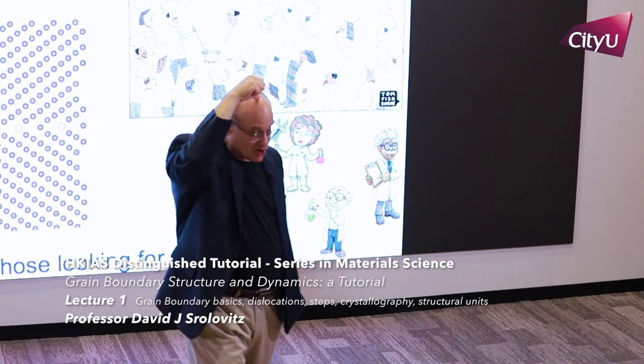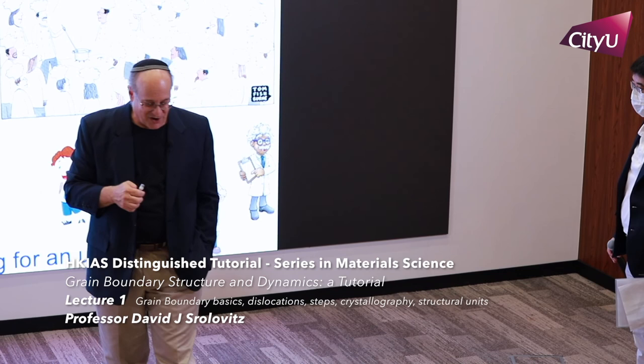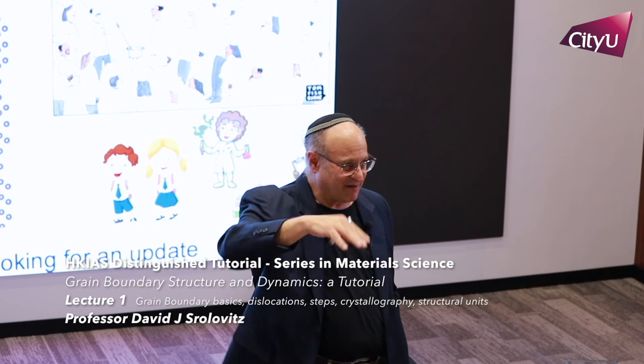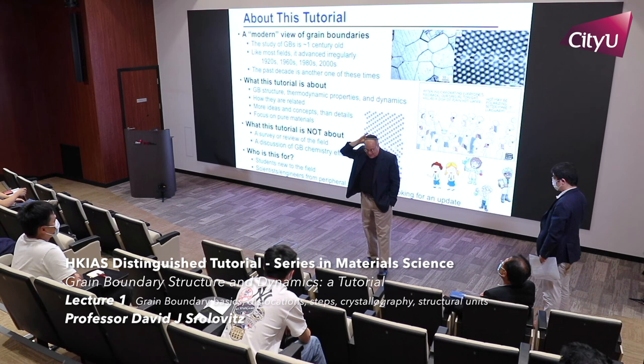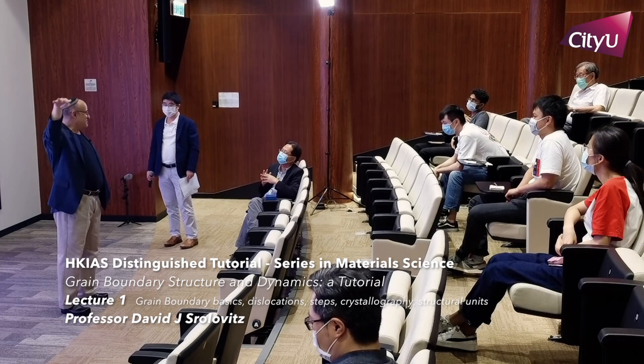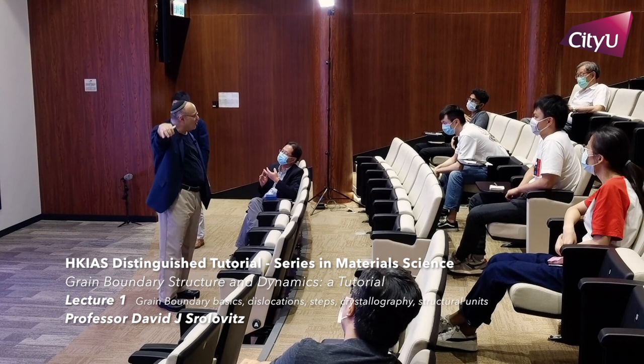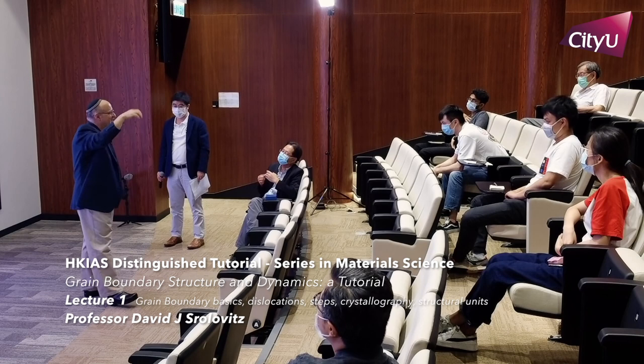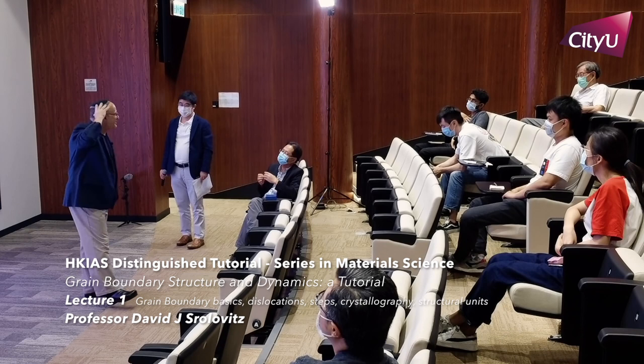If it's an ordered alloy and you have a substitutional solid solution all the way across, then it's not so bad. If you take something very strongly ordered, say nickel 3 aluminum, and as long as the substitutions are other things which are substitutional, it's very straightforward to do this, because I can calculate the energy of putting that atom into the core of those units. And since I also know a little bit about the misfit, I can also predict the elastic effect. But those are not the interesting cases.